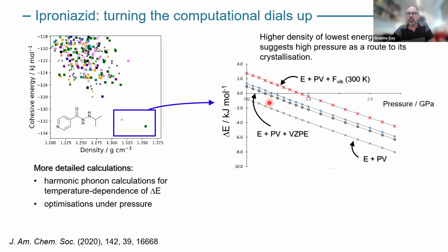When you put in those vibrations, even if you don't put in any temperature, but you just look at zero-point vibrations of the atoms in the crystal structures, that order swaps. Okay, so now the one that we're seeing in the lab is actually the global minimum, still at 0 Kelvin, but it's just that we had to take into account the fact that atoms are in motion in our crystal structures. If we put temperature in, say up to room temperature, then you get to this red point here, and it's just increasing that difference. So now this observed structure is getting even more stable compared to this one over here. So that's explaining what we're seeing in the lab when they're doing those experiments in Durham.